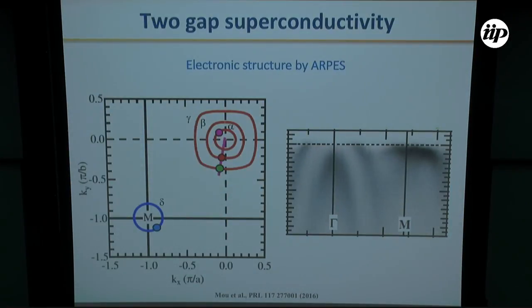ARPES data have also been taken on the same samples by the group of Kaminski. They have found 3 hole pockets around the gamma point and 2 electron pockets around the corner of the Brillouin zone. The inner gamma hole pocket, alpha, disappears close to the Fermi level, and they have found an open superconducting gap over the whole Fermi surface, also with 2 different values of the superconducting gap. These 2 values are well separated in the Fermi surface, which also favors S plus minus superconductivity.